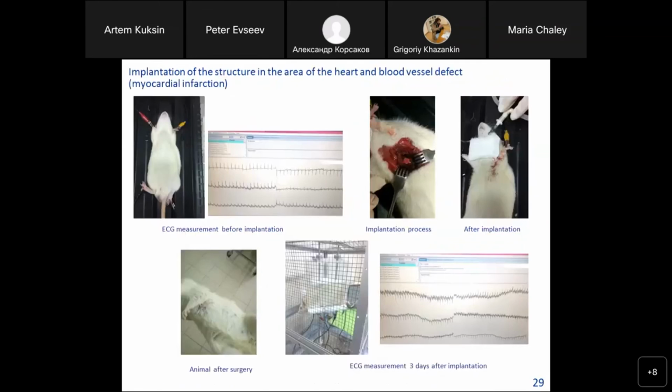Before experiments in vivo, we carried out studies of the hemocompatibility of nanomaterials. We investigated blood hemolysis after its contact with nanomaterials. The value of hemolysis was no more than 1% for nanomaterials based on 3 types of biopolymers. It was albumin, collagen, and chitosan.